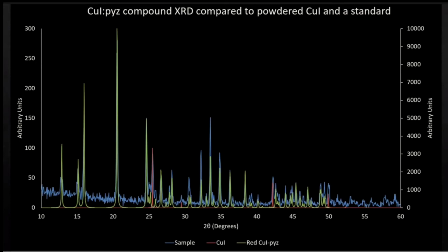Then we wanted to further verify with X-ray diffraction to see if we did in fact get the red polymorph. X-ray diffraction is kind of the standard way to identify these compounds, standard way to see what you made. And it's important to note that on the y-axis, this is unimportant, this is arbitrary, but the x-axis is very important. And the idea here is we blast a sample with X-rays and we measure the angle of deflection that you see whenever those X-rays bounce off. And so this can tell us a lot about the crystalline structure of the product.